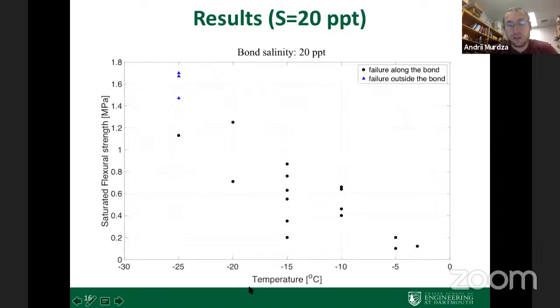So the next set of data was obtained at a constant salinity, 20 ppt, for all the tests. And we varied the temperature of freezing, the air temperature and ice temperature during which the freezing occurred. And again, it's a saturated flexural strength. And so you see, as we lower the temperature, the strength increases, as we would expect. And at -25 Celsius, in most of the samples, failure occurred outside of the bond, indicating that the bond is already at least as strong as the parent material and probably stronger.